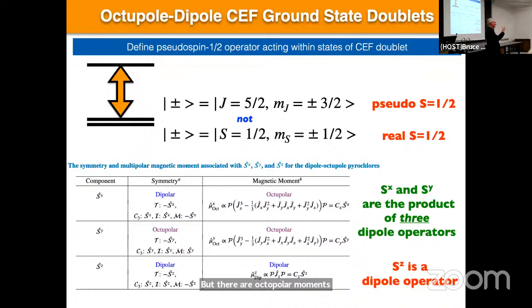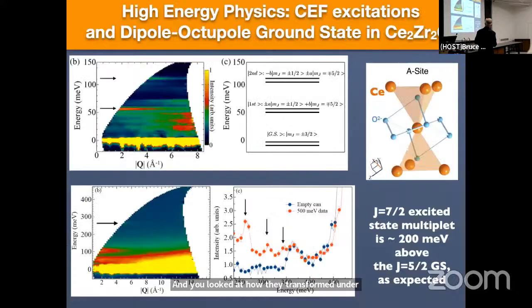Okay? And it's a little bit more complicated than that. If you looked at these either octupolar or dipolar magnetic moments in real space, and you looked at how they transformed under the point group operations for the cerium site. Okay, so that's the symmetry operations associated with this particular site here, which basically are a threefold rotation axis and a mirror plane.